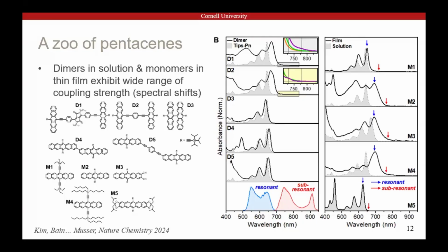So we have these covalent dimers that are connected by a unique chromophore, a phenyl bridge, or no bridge at all. We have them in the 6,6' geometry and this 2,2' geometry. And then we have a family of thin films that pack into strong H aggregates, strong J aggregates, very weak J aggregates, and a system with no evident coupling between the pentacenes at all. All of them do singlet fission, but we wanted to go one question further.